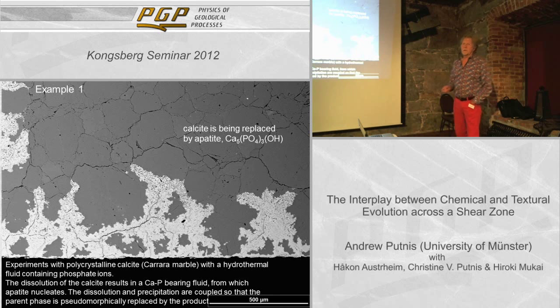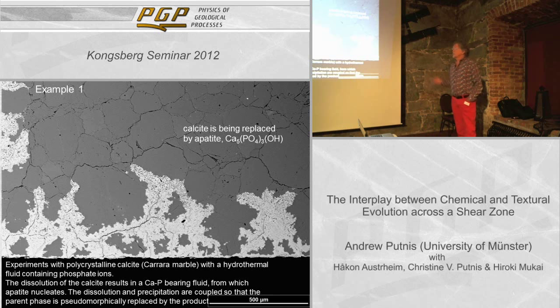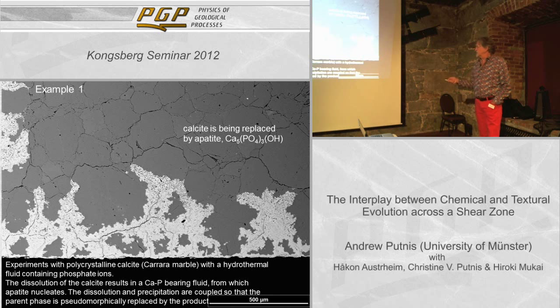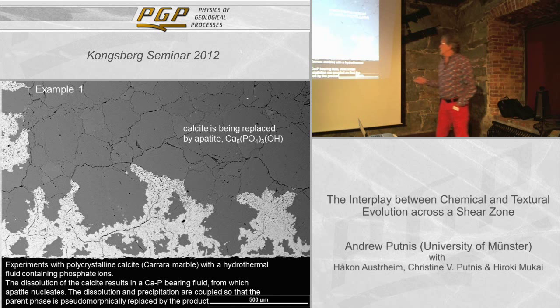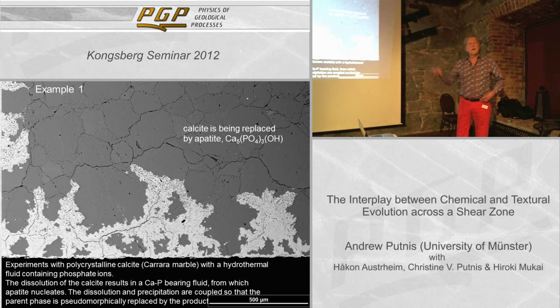Here's an example of a very simple experiment we do with undergraduates. This is Carrara marble — it has the advantage that it's actually got grain boundaries and a nice grain size of 500 microns. If you just take Carrara marble, which is pretty pure calcite, and put it into a solution of ammonium phosphate — just something containing phosphate ions — clearly, calcite is out of equilibrium with water with phosphate ions in it. It'll begin to dissolve, and the calcium from the calcite interacts with the phosphate, and calcium phosphate is very insoluble, and you produce apatite.